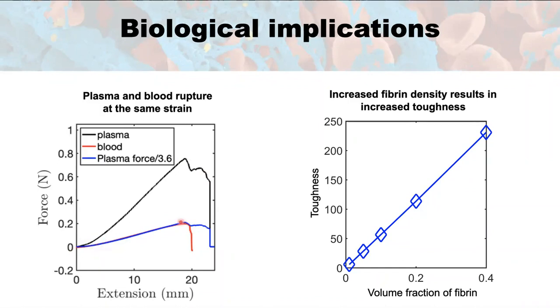And so then if we take the model and we normalize it to the amount of plasma or fibrin that would be present in that whole blood clot, we see that there is good overlap between the plasma force from the model that's generated and our whole blood curves. So again, pointing to the fact that fibrin is that main mechanical component of the clot, and what's accounting for much of the rupture process, which is important again for our experiments and for understanding the biological implications, but also for potentially informing the embolization process of thrombi, which are inherently more complex.